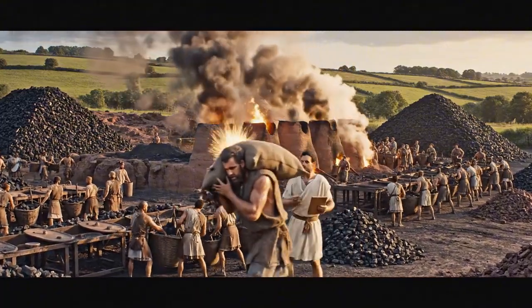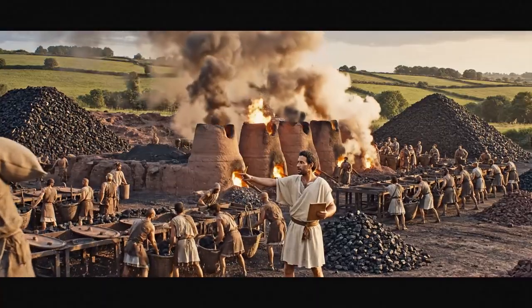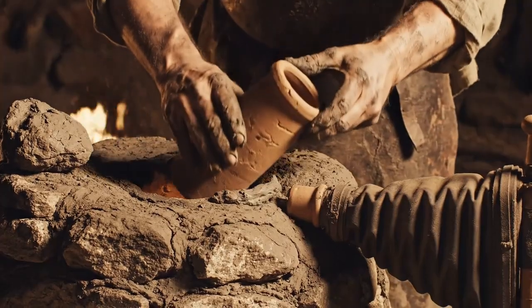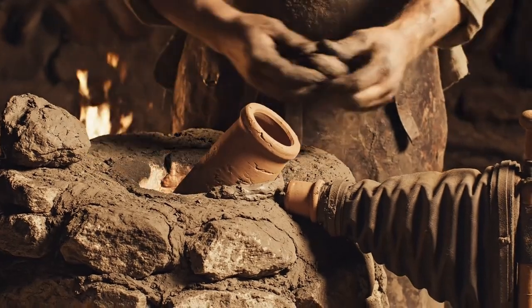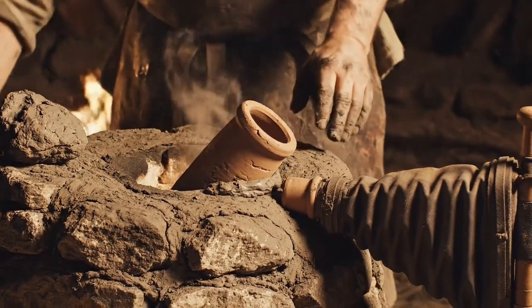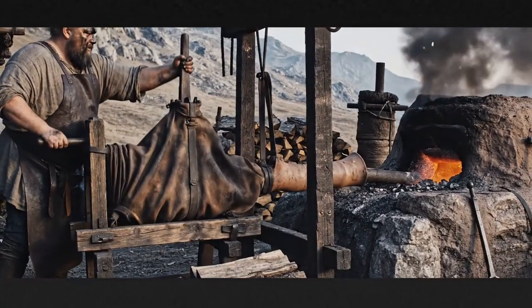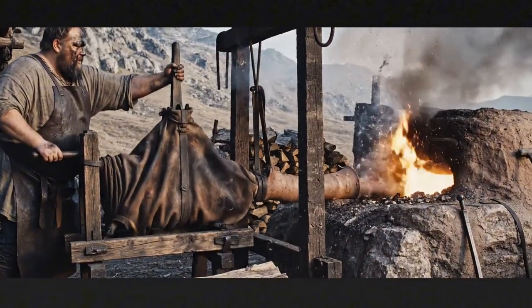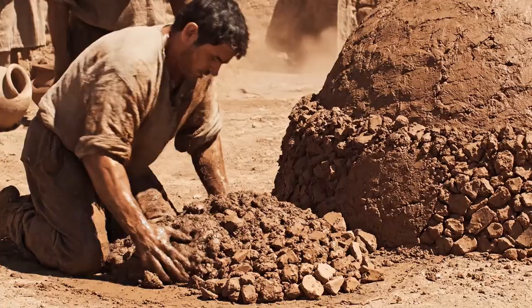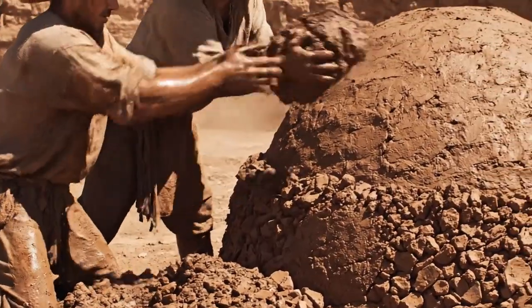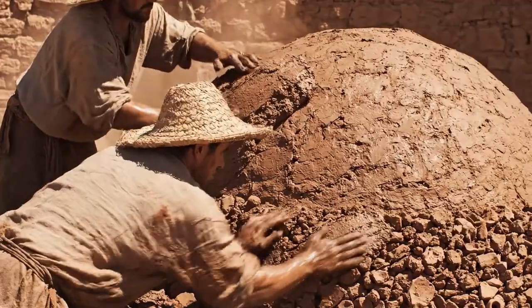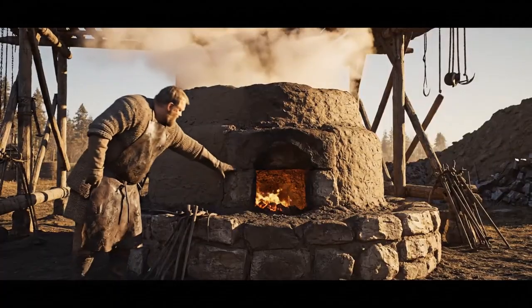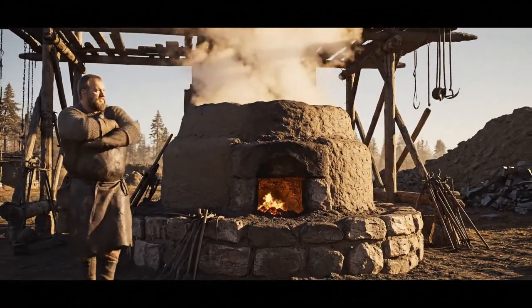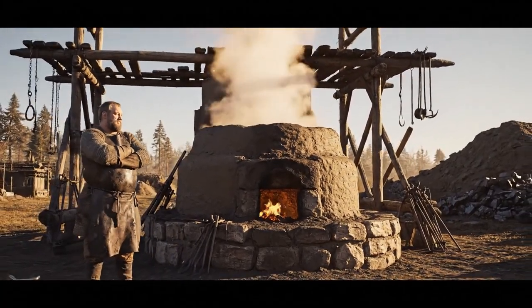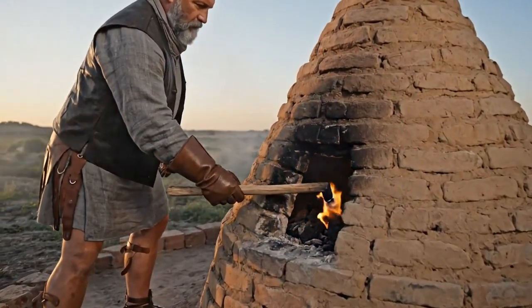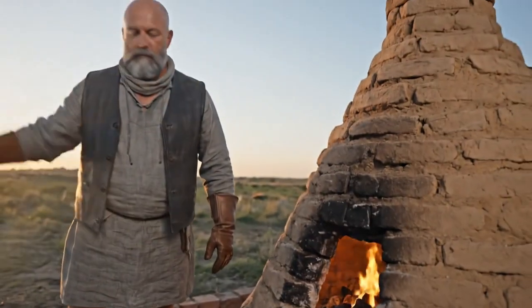Roman smelters in Britain and across the empire typically used shaft furnaces constructed from clay, rising 50 to 80 centimeters above ground level. The interior walls were thick enough to withstand temperatures exceeding 1200 degrees Celsius, and a small opening near the base allowed for the insertion of clay tuyères, the tubes through which bellows would force air into the combustion chamber. Building the furnace was itself a craft requiring days of work, as the clay had to be mixed with sand or crushed pottery to prevent cracking under thermal stress. The furnace was dried slowly over several days, then pre-fired with gentle heat before the first real smelt could begin.